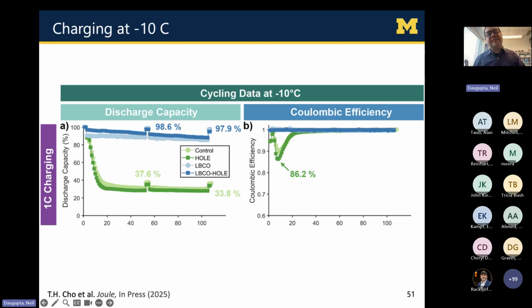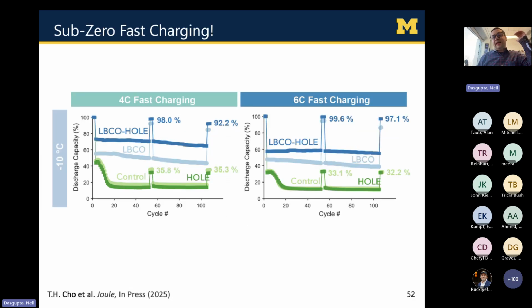These data are showing, fast charging, or I'm sorry, even slow charging at a temperature of minus 10 degrees Celsius. What we see is even if you just do 1C charging here, the control electrode quickly fades. But if we look at the combination of the LBCO ALD coating and the holes, we're able to maintain greater than 97% capacity retention at a temperature of minus 10 degrees C. And note this is with no external heating, no thermal management of the battery. It means you could just cold charge the battery without plating.